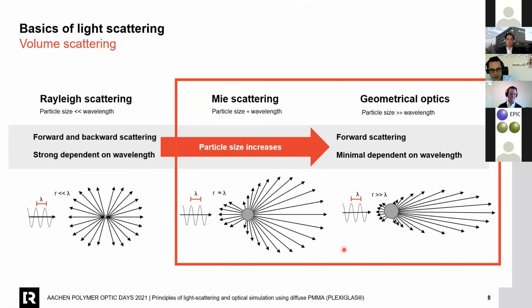So if we take a look at different particles, there are inorganic particles, there are organic particles. If we distinguish by the size of these particles, we have to take a look at Rayleigh scattering. Here, the particle size is much, much smaller than the wavelength of the incoming light. Rayleigh scattering shows strong scattering forward and backward. So there is no preferred direction of the light, and it's strongly dependent on wavelength. This happens in gases or the atmosphere, humidity in the air. This is Rayleigh scattering. For plastics, the Mie scattering and the geometrical optics are more interesting.